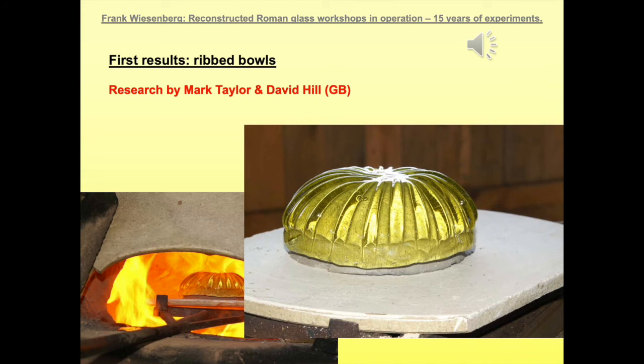The flat disc with the pinched ribs can be transferred onto a hemispherical mold again and can be slumped over this mold inside the glass furnace. Also, this might require a couple of manipulation processes by the glass makers with frequent reheating.